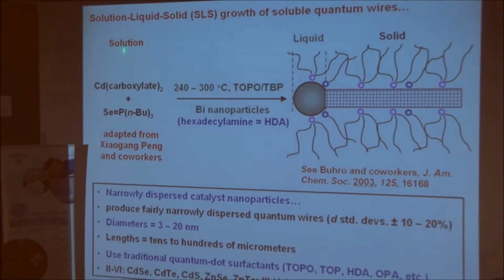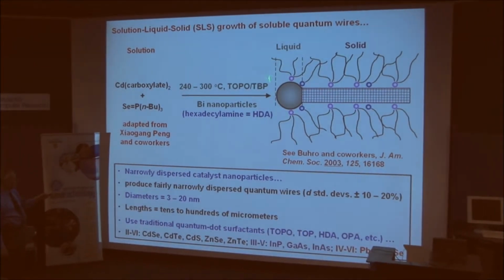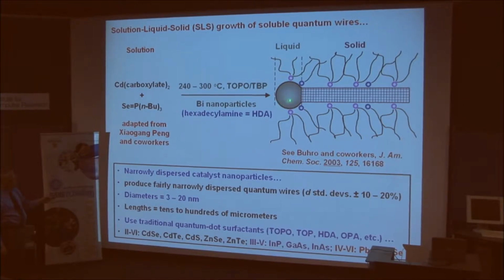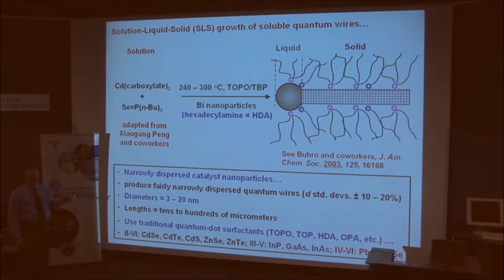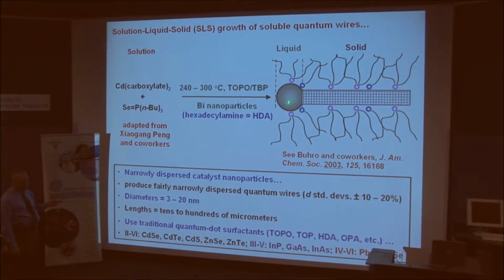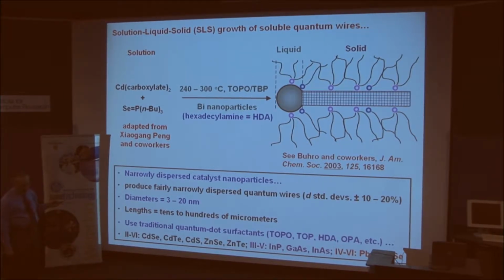The precursors to the semiconductor phase decompose in solution at the interface between the solution and the liquid catalyst droplet, because under the reaction conditions, the catalyst droplet is actually molten. It's a liquid. And that deposits the elements of the semiconductor phase into solution in the metallic droplet. The metallic droplet becomes supersaturated, and to relieve the supersaturation, it has to precipitate the semiconductor phase. It does so by forming a liquid-solid interface and precipitates the semiconductor as a crystal.